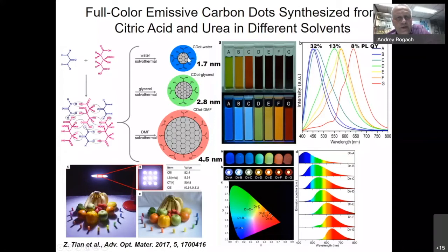So when we made synthesis in water, we made smaller nanoparticles, and their polyaromatic domains were the smallest ones, so they emitted blue light. And when we ran the synthesis in glycerol, we made bigger particles, they emitted green light. And when we ran the synthesis in DMF, we made the biggest particles and they emitted red light. But you can see from these nice photographs here that we can make any color in between as well. So this is really a beautiful example of full spectral tunability of emission color of these materials.